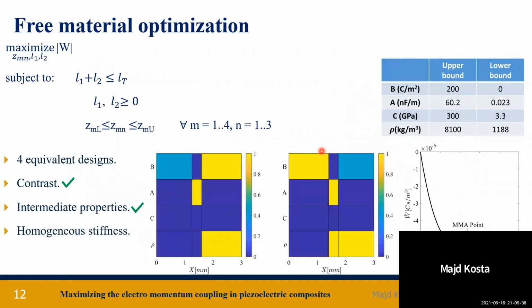Now, for the next problem that we considered, we unleash the physical constraint between the material properties, where we aim to optimize W over the material properties and the length of each layer simultaneously. This will give us a theoretical upper bound on the value of W and establish a rule of thumb on the optimal design. And to ensure that we obtain a meaningful result, we apply an upper and a lower bound on the material properties. And these material properties were normalized following this upper and lower bound.